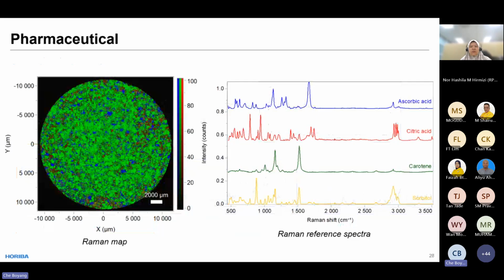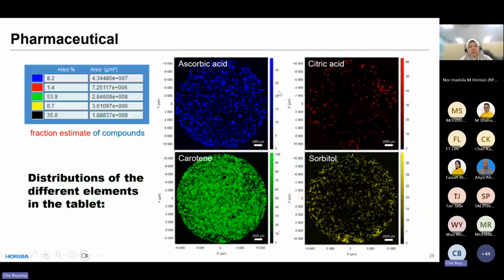So this example is on the pharmaceutical sample. We are mapping a full vitamin C tablet. So this size is quite big. It's about 20 millimeter. And within this tablet, we have 4 different components. So we can get the distribution of 4 different components here, and we can study how API is distributed within this tablet. And moreover, based on this image, we can also get an estimation about the fraction of the components based on the area it occupies.